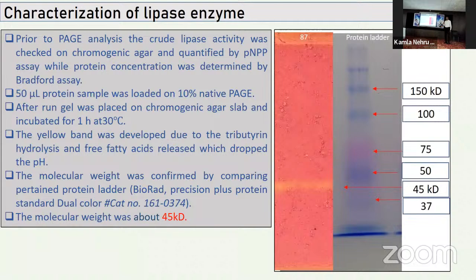Then we tried to study what kind of lipase enzyme it has. We did not, of course, purify it, but we did native polyacrylamide gel electrophoresis, where the enzyme is not denatured and you can visualize it by activity staining. The activity staining was done on chromogenic agar, where we simply add substrate along with indicator. Because of hydrolysis, fatty acids will be released, pH will decrease, and a color change will be observed. So red showed yellow color, clearly showing activity, and we compared it with our protein ladder, and it shows around 45 kDa. In literature lipases are normally dimers, so maybe it has a monomeric molecular weight of 22.5, or between 20 to 25.